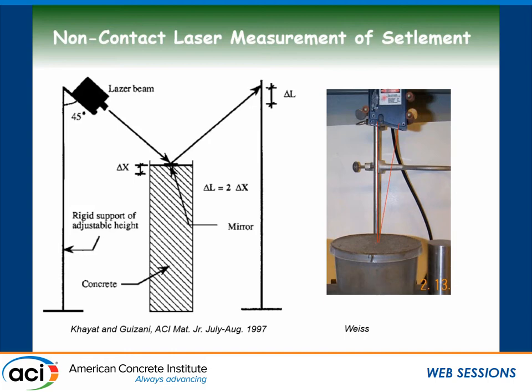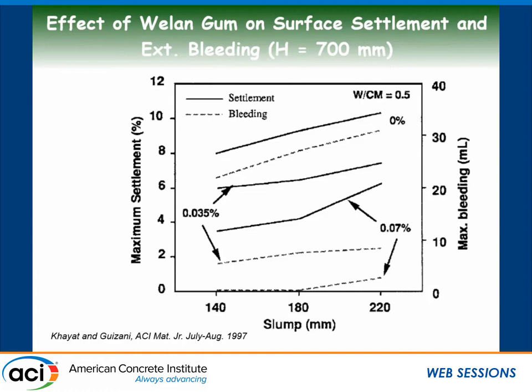If you look over here at the surface settlement versus slump of the concrete. So this is, again, an old study for flowable concrete with slumps of 140 all the way to 220 millimeters. So 6 inches going to 8 inches, with a concrete of a fixed water-cement ratio of 0.5. So if you simply add superplasticizer and you look at the surface settlement in solid, the surface settlement is going to increase. And then if you start putting some viscosity modifying admixtures, in this case welan gum, you can reduce it. If you put more, you can reduce it further.